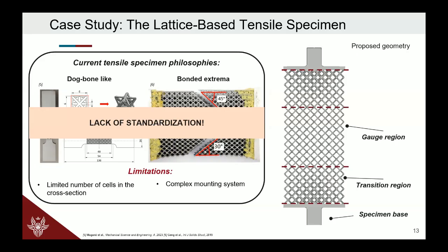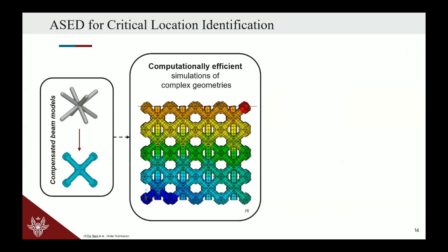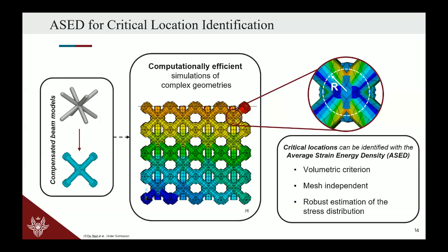So we studied the problem properly, and the idea was to have a computationally efficient simulation for complex structures. We use the strain energy density approach, which is very good for studying the nodes of this structure, which are the critical points, where we can consider a volumetric criterion. We have the advantage that the criterion is mesh independent, so we don't have to take into account mesh refinement. And we have a robust estimation of the stress distribution if we first consider the strain energy density and later the stress.